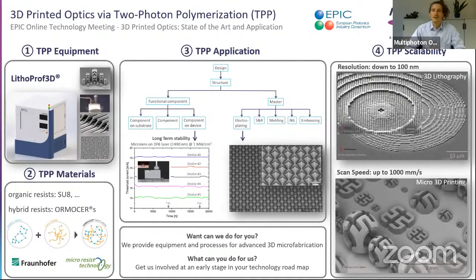So on the right side, you see a metal lens, and this consists of different pillar sizes down to 100 nanometer and up to 450 nanometer. And also the scan speed. So we showed up to 1000 millimeters per second, which you can see on the bottom right picture. And the structures are up to a millimeter times a millimeter times a millimeter.